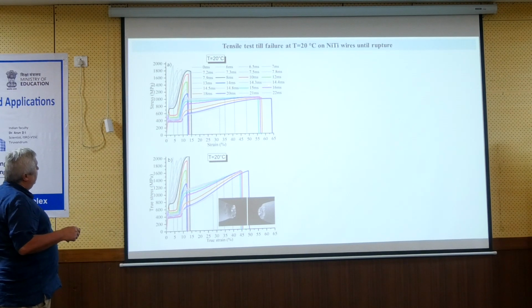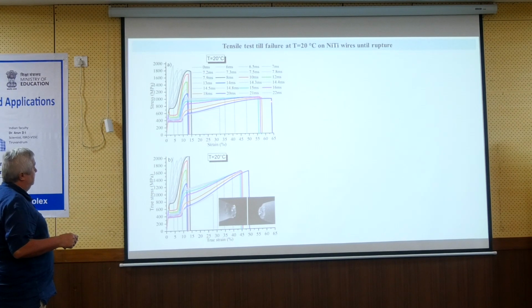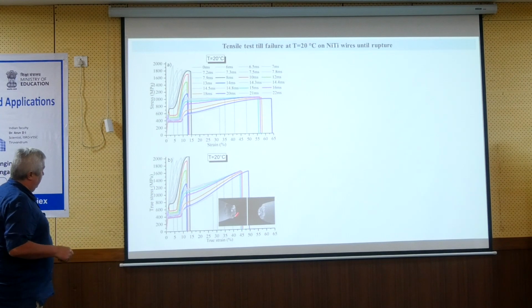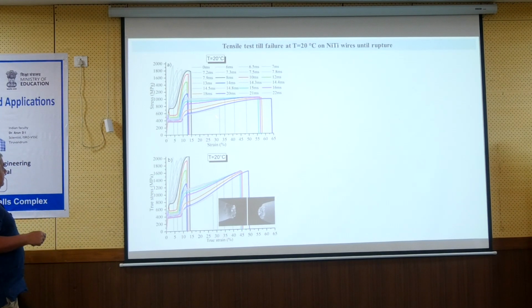But somewhere around here, the blue, 14 to 15, suddenly you will go up to 65%. Here there will be a plateau and then it goes down. But if you plot it in true stress, true strain, this plateau, like the cyan, for example, becomes still hardening. So in reality there is still hardening, but there is this transition from low ductility to high ductility, which occurs somewhere between 14 and 15.